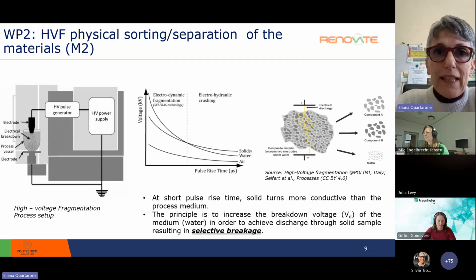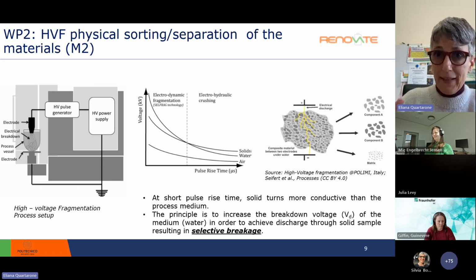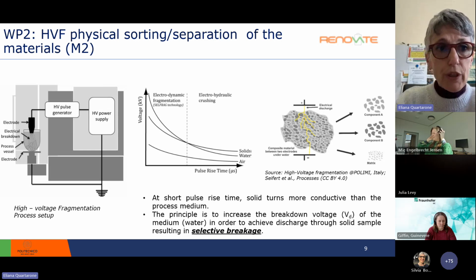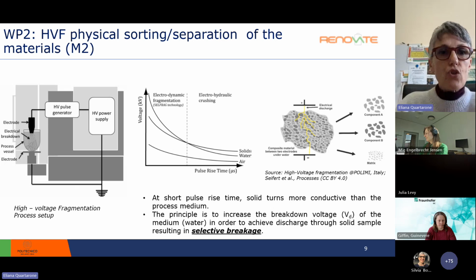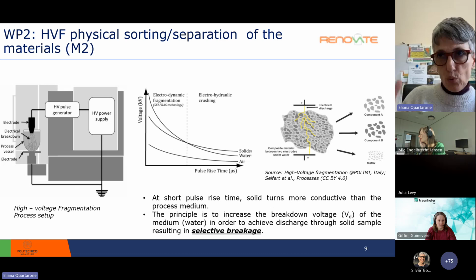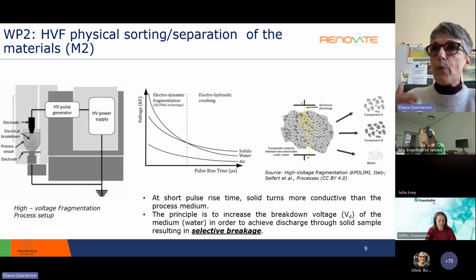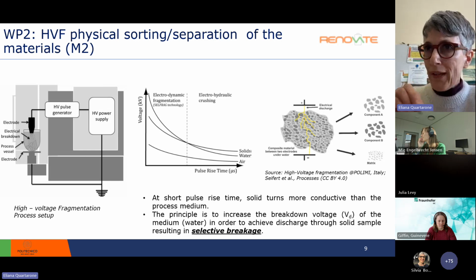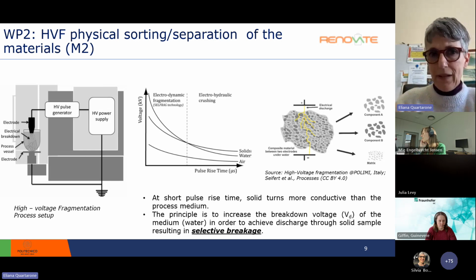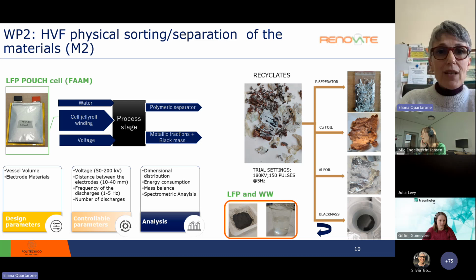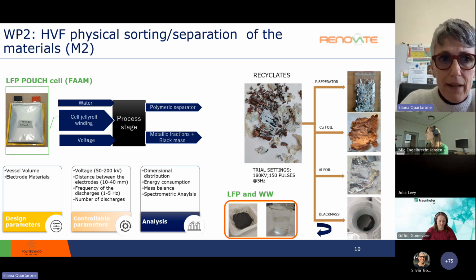The basic principle is to put the cell directly, sorted from the module of course, in a water medium between 2 electrodes, and apply a high breakdown voltage in the water in order to achieve discharge to the solid samples, resulting in the selective breakage of the single components of such mixed or composite materials. And the results are there, because we are working on failed cells coming from FAAM, a big cell made by 30 layers in a pouch cell.